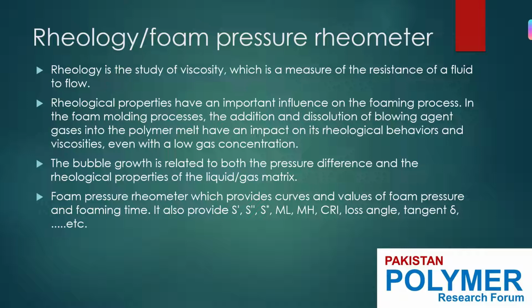So whenever a blowing agent is mixed with the polymer, there is a certain rheology involved that can be checked by the addition and dissolution of blowing agent gases into the polymer melt. Because the melt experiences stress by both shear and extension, the rheological behavior of polymer melt has a significant influence on pressure distribution inside the mold. The pressure distribution will have impacts on the polymer gas distribution and the polymer melt flow. What is more, the viscosity of the melt has an impact on the pressure drop of the melt through the mold, thereby influencing the nucleation and growth of the bubbles down the line.